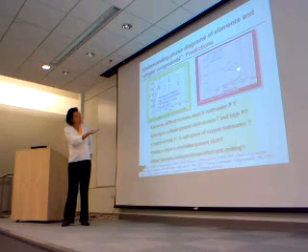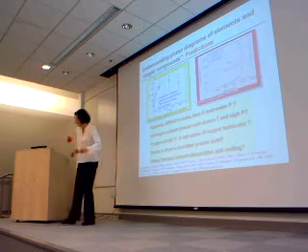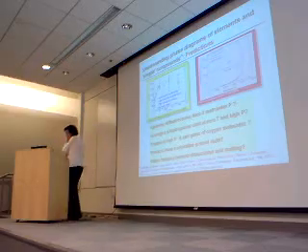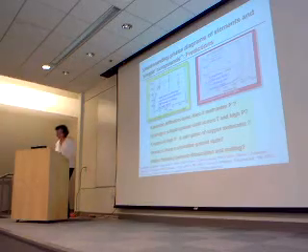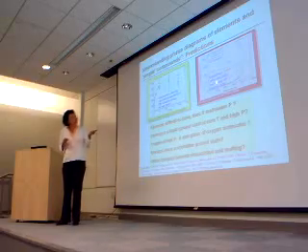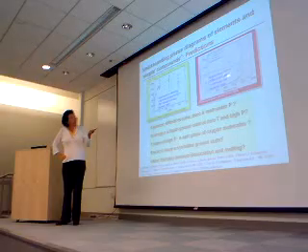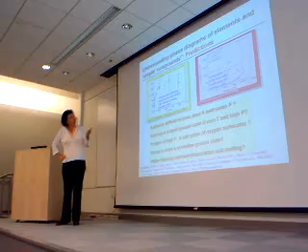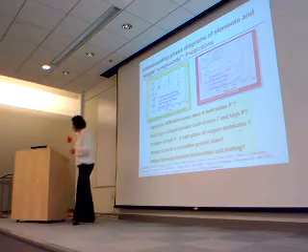There was a prediction of a triple point here and of what would happen to diamond under pressure, done using simulation, and the prediction was confirmed one year after the calculation by experiments done in France and at the Lawrence Livermore lab using laser-shocked materials.